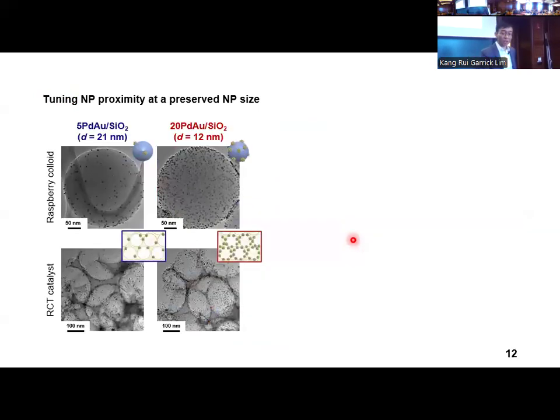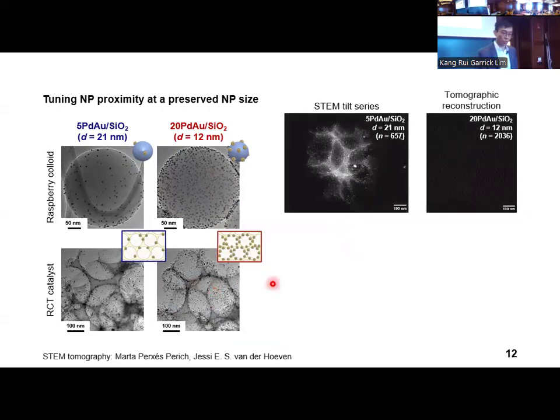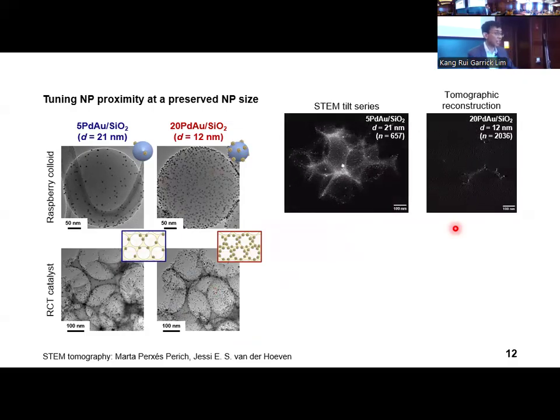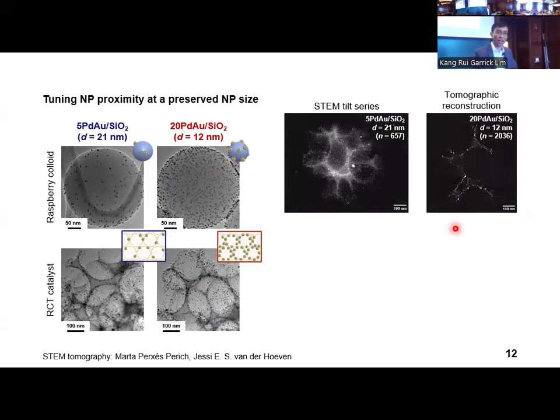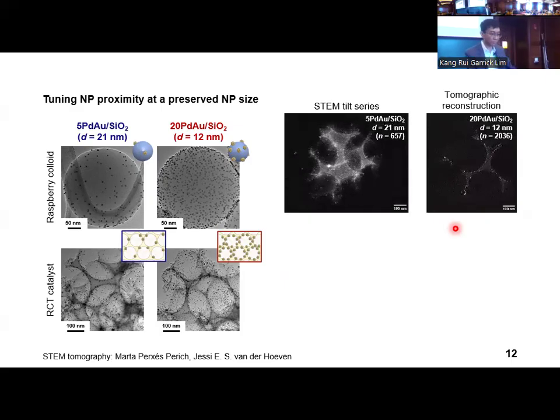As expected, we found that a higher metal loading resulted in a higher nanoparticle density and thus shorter average interparticle distances. You can see this in both the raspberry colloids we used and the RCT catalysts we produced. To quantify the average interparticle distance of our three-dimensional catalysts, we used electron tomography to determine the three-dimensional spatial positions for each nanoparticle for over 2,000 nanoparticles. We then wrote a script to find the shortest interparticle distance for each nanoparticle within each pore.